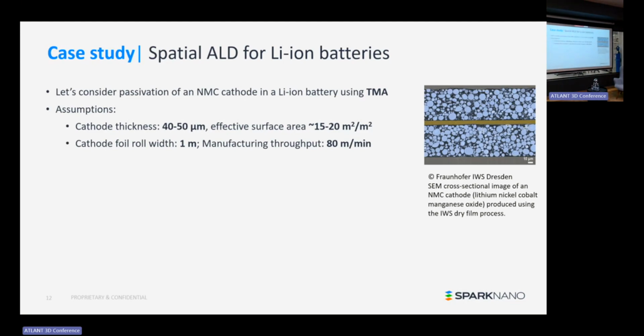There are certain tricks you can do. For example, in spatial ALD, we do not deposit on the reactor walls, which already saves some precursor. We can also do tricks to minimize the unwanted deposition. If you really do the math correctly, and optimize your process correctly, you can go up to things like 70% precursor utilization efficiency in the process. 70, roughly. Again, it depends on the speed and the throughput that you need. It's easier on a porous substrate to achieve high efficiencies than on a planar substrate.